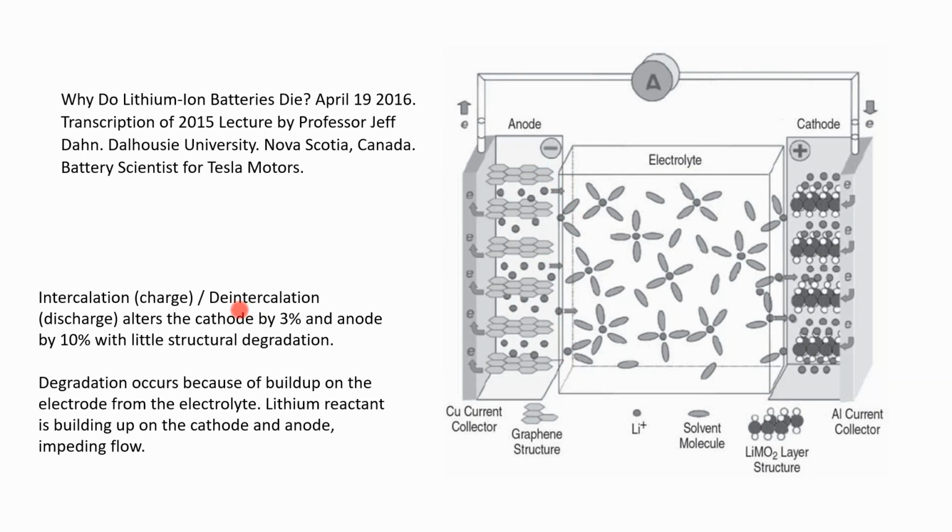And you measure the mass of a cathode and an anode under a failed battery, and the anode changes by about 10%, and the cathode doesn't change very much, by about 3%. And so what that means is, inside the anode, it still has a lot of mass that could degrade if somehow we were to put a whole bunch of plates into an electrolytic mixture and increase the surface area of the anode.